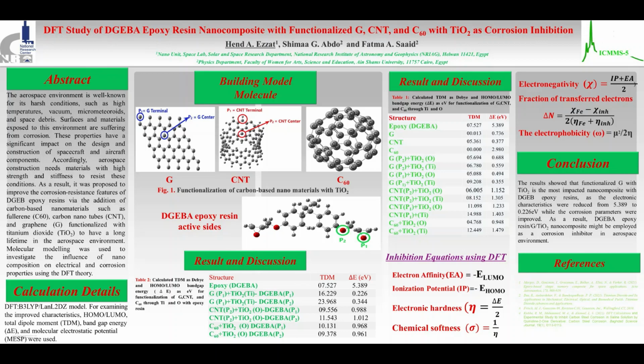Accordingly, aerospace construction needs materials with high strength and stiffness to resist these conditions. As a result, it was proposed to improve the corrosion resistance features of DGEBA epoxy resins via the addition of carbon-based nanomaterials such as fullerene, carbon nanotubes, and graphene functionalized with titanium dioxide to have a long lifetime in the aerospace environment. Molecular modeling was used to investigate the influence of nanocomposition on electrical and corrosion properties of epoxy resin using the